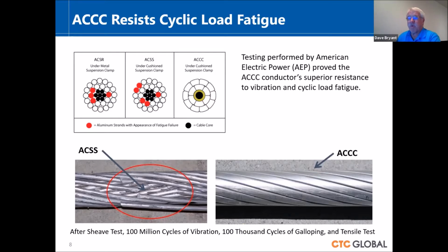But I think one of the most important things for reliability in terms of overhead conductors is that many of them experience cyclic load fatigue, or in the case of the picture here in the ACSS conductor, you have fretting fatigue because the vibration causes the small contact points to rub back and forth against each other, which then causes microfractures to propagate and the conductor strands to actually break, which can then lead to conductor overheating and then ultimate failure of any type of core.